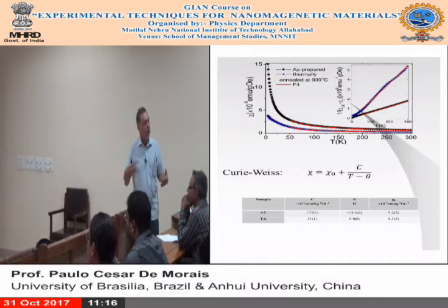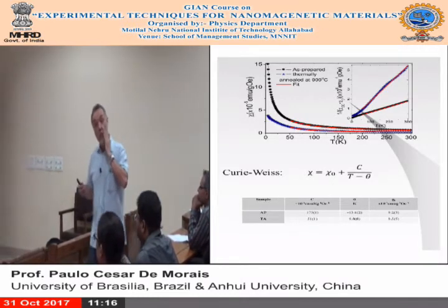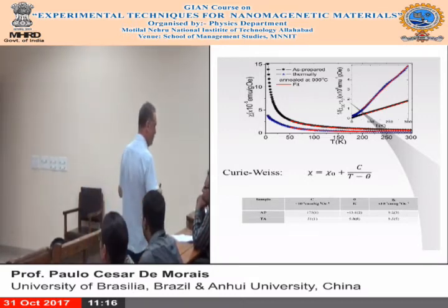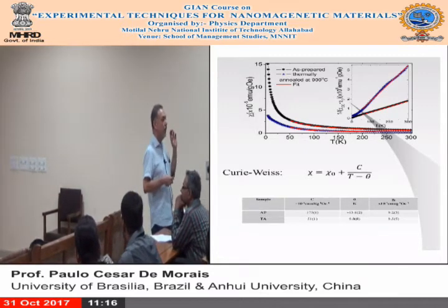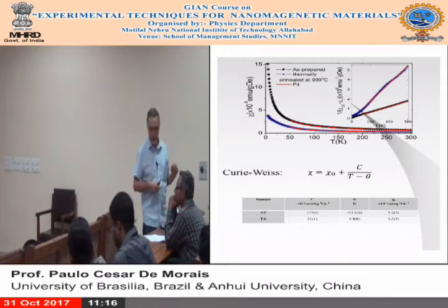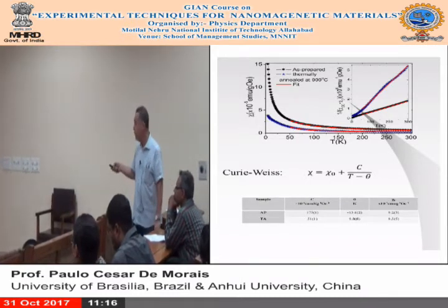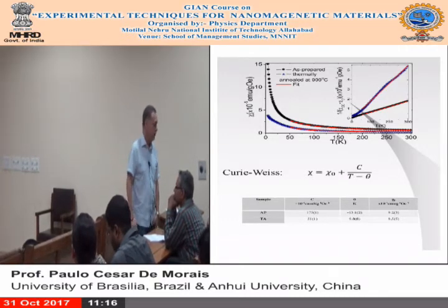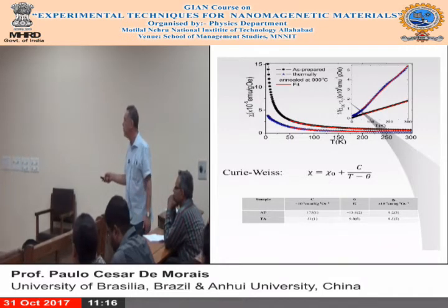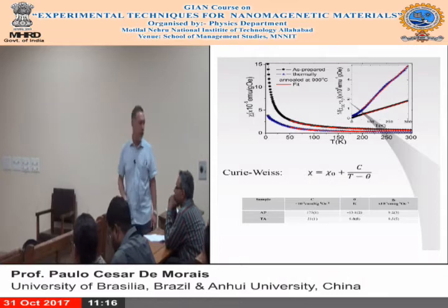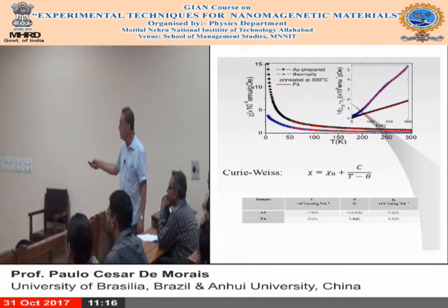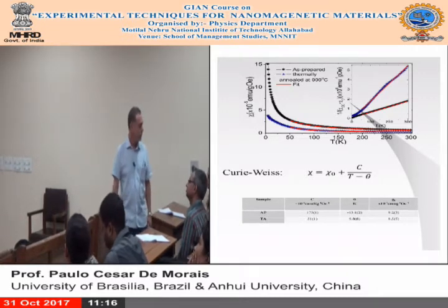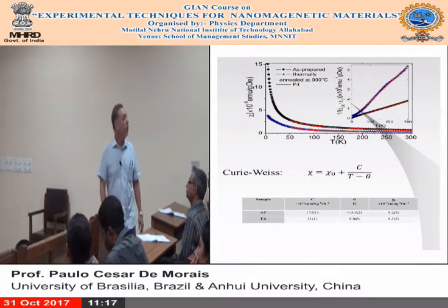So we already made a hypothesis: not only one phase, it was phase separation, it was formation of some glass clusters, okay? And those glass clusters are responsible for the negative crossing of the straight line. So they are responsible for the negative theta temperature. But when we make annealing, look at the data. The susceptibility just drops down very much, and it is not straight anymore.